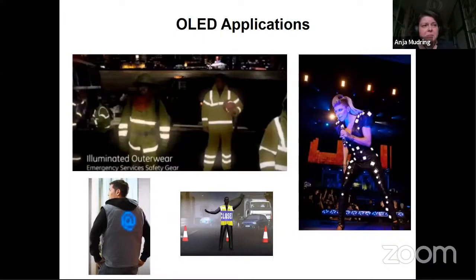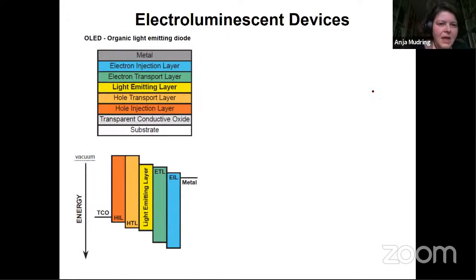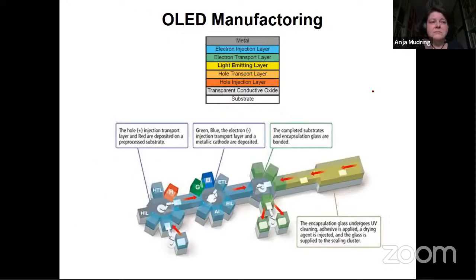One application I consider to be important is active light emitting clothing. So for example, when you have workers at night on the streets, you have something where it's not just when you drive up with a car that reflections come up and you see there's a person, but you are actively illuminated and give a signal even to those that wouldn't see you otherwise. And here we have the OLEDs. They're still very expensive to manufacture because you're injecting, like with the LED, the electrons and holes, and you have to make sure that they get transported to the light emitting layer and recombine there. And that's where you generate the photons. You have to give a lot of thought to the thickness of the individual layers and so on.